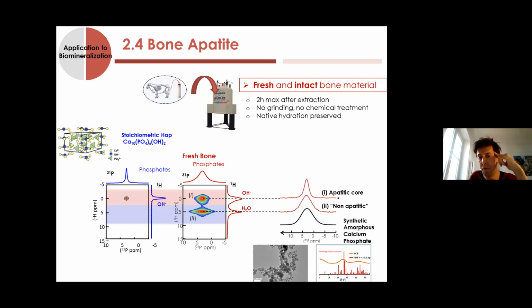Here you have something which is about Lorentzian, corresponding to something crystalline. And here you have something broad, which is Gaussian, corresponding to something amorphous, perfectly comparable with a synthetic sample. This means that the crystals in bone are made of two different domains: one crystalline in the core, and one amorphous at the surface.